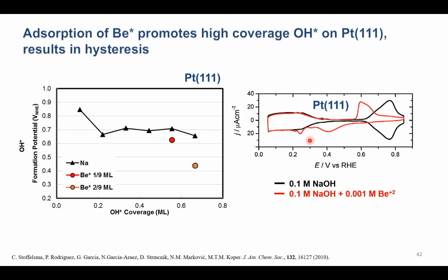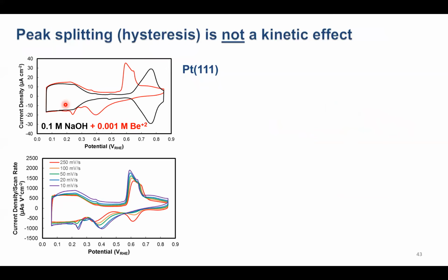And so what I did is I then repeated these measurements in platinum 111. So it's shown on the left here. And then I measured CVs as a function of scan rate. And if this were due to kinetics, the peak in the forward going scan and the negative going scan should move closer together. There's kind of a lot of things that are changing here, but importantly, we do not see these two peaks come closer together.